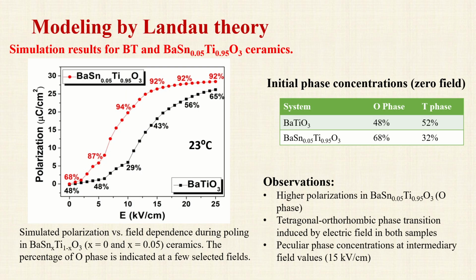In this graph, the first polarization curves that correspond to a poling process are represented for unpoled and poled barium titanate, doped and undoped. Both samples present phase superpositions at room temperature, which was considered 23 degrees Celsius. The orthorhombic phase is favored in solid solutions, and therefore the polarization values are generally higher.